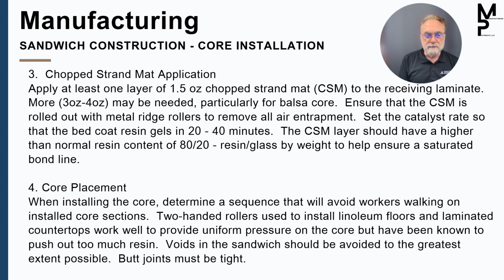So now that you've got the core down on the part, one thing you don't want to do is press really hard on it and then take that pressure off. So if you manage to position it such that now you've got to step on the core to get out of the product, to get out of the way, once you step on it, you're going to squish all that resin out of the core. And when you take your foot off, guess what's going to replace that resin? Yep, air. So look at how you're staging it so you can avoid walking on any of the cores.